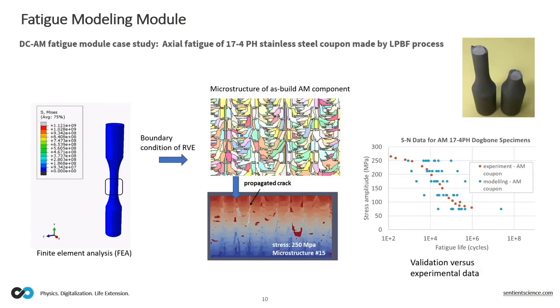I'm showing a couple of use cases here. First one is the simplest case that we can do on fatigue, just a simple dog bone under axial loading. The simplest case of fatigue testing that we can do. This one was made by powder bed for stainless steel 17-4. As you can see again, we did the prediction of the microstructure and then did the fatigue testing and also fatigue simulation.